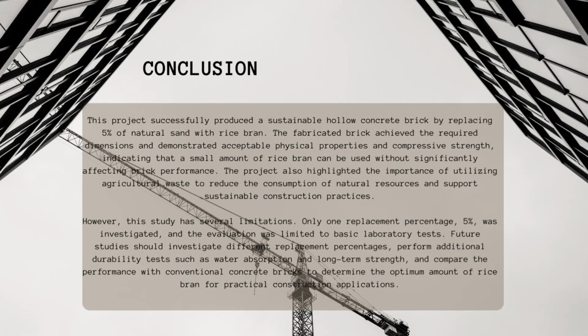In conclusion, this project successfully produced a sustainable hollow concrete brick by replacing 5% of natural sand with rice bran. The fabricated brick achieved the required dimension and demonstrated acceptable physical properties and compressive strength, indicating that a small amount of rice bran can be used without significantly affecting brick performance. The project also highlighted the importance of utilizing agricultural waste to reduce the consumption of natural resources and support sustainable construction practice. However, this study has several limitations.